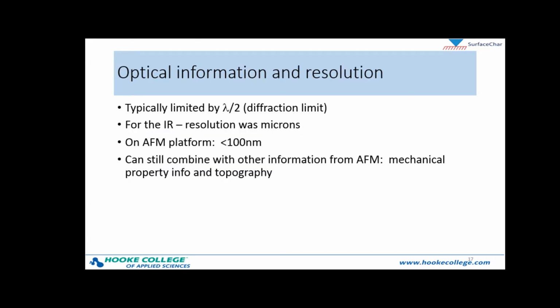Now, before we go into some of the AFM-IR examples, I just wanted to say a few words about resolution and this optical information. So typically, optical spectroscopy measurements such as Raman and IR are limited by the diffraction limit, which is lambda over 2, where lambda is the wavelength of the incident light. For the IR, which typically has very long wavelengths associated with it, that meant the resolution was limited to microns. So to be able to put this onto an AFM platform and achieve resolution of less than 100 nanometers very easily, and in some cases even less than 20 nanometers, is very impressive.